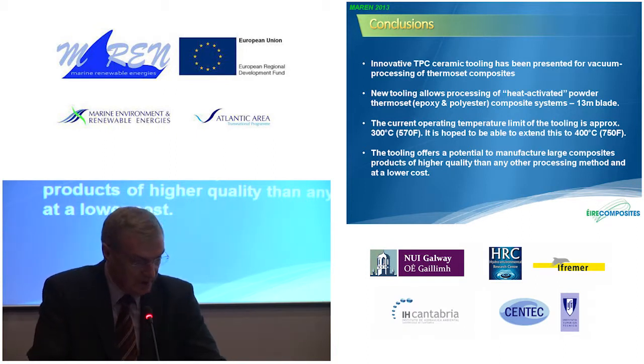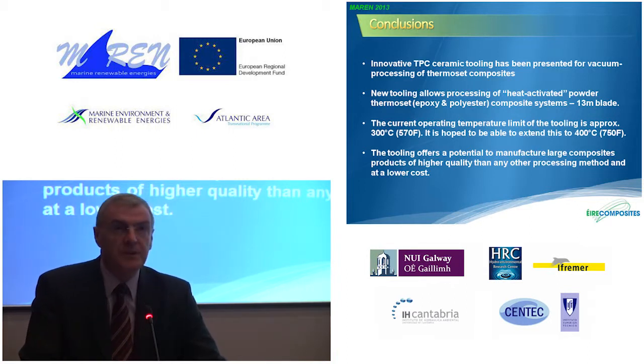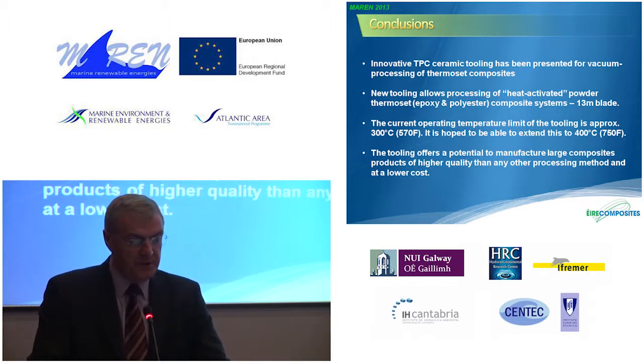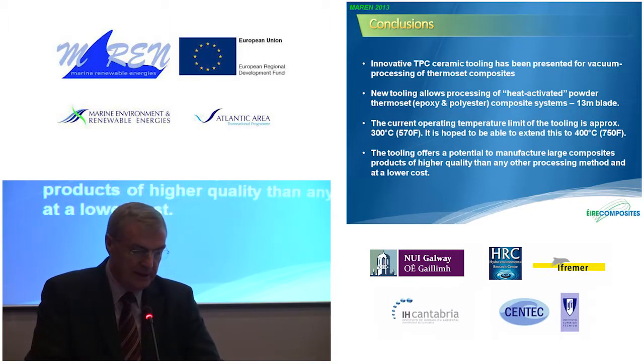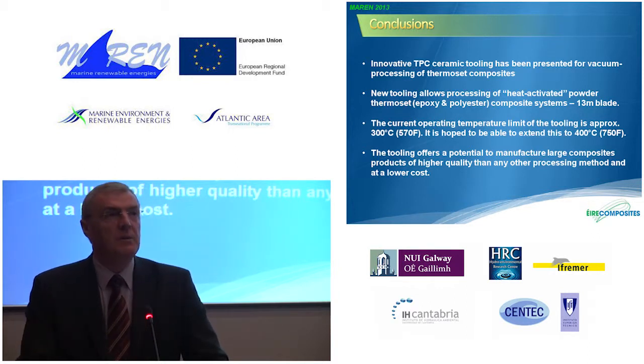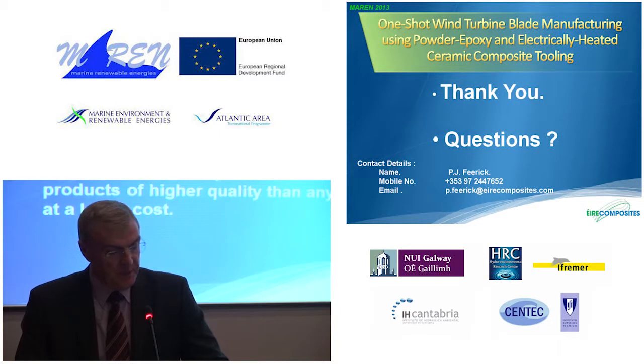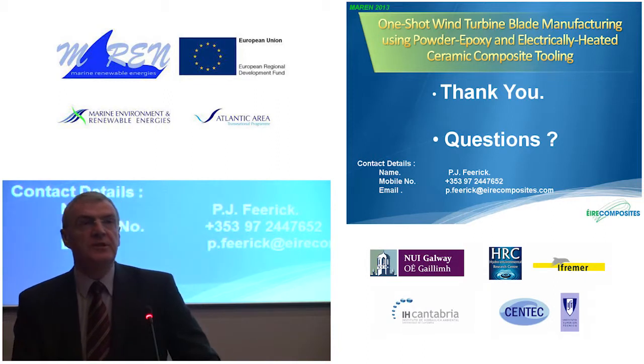13-meter blade. We currently have a limit of about 300 degrees centigrade at the moment, and we're developing the tooling further to get it to at least 400 degrees for the processing of materials such as PEEK, etc., which requires higher temperatures to do this. And this system also offers potential to manufacture large composite products with a higher quality than existing processes, and also at a lower cost. Thank you very much for your time.